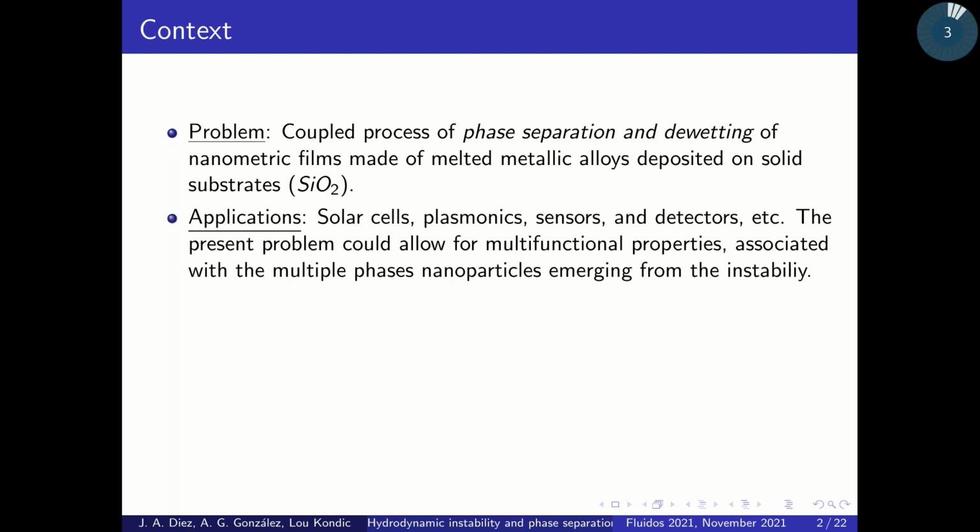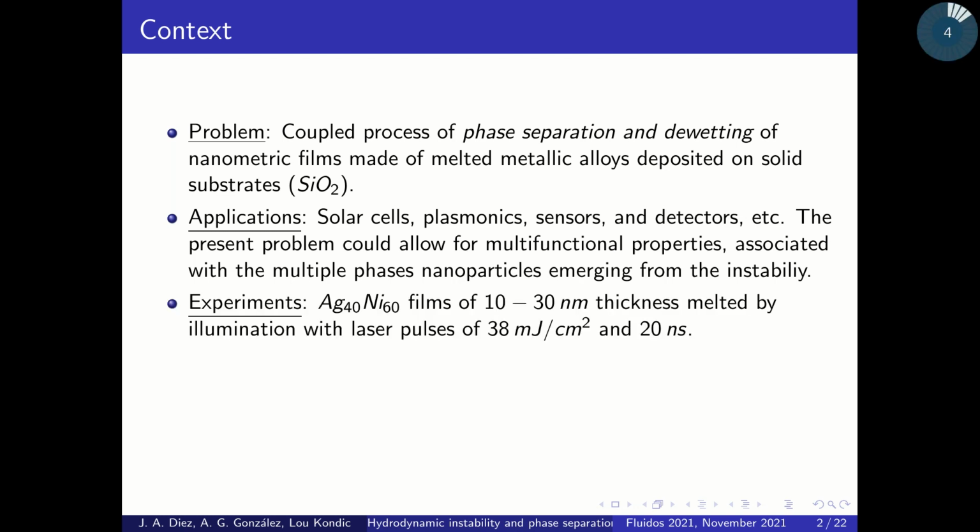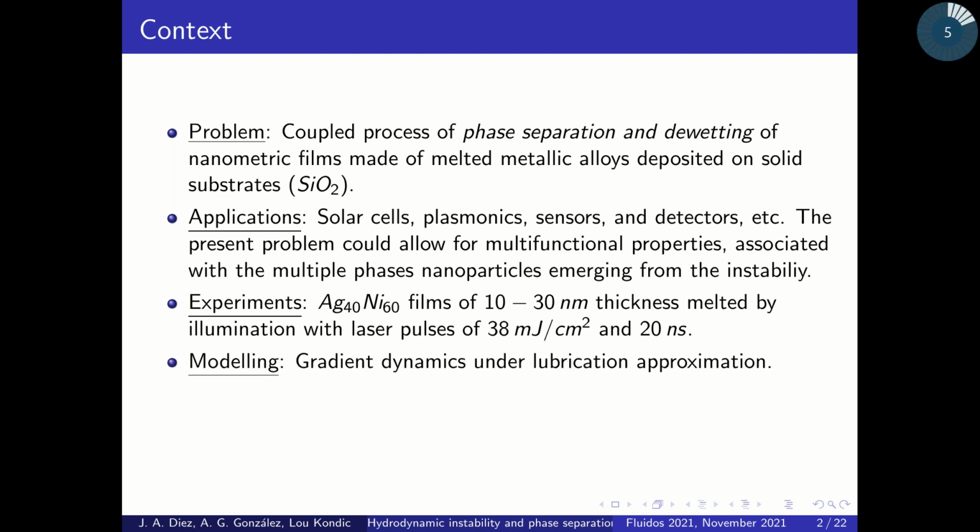This problem is of interest in applications because it gives place to the formation of nanoparticles where the metals are separated, and this can be related to multifunctional properties. The experiments are made on silver and nickel, and the films are melted by illumination with laser pulses of a duration of about 20 nanoseconds.